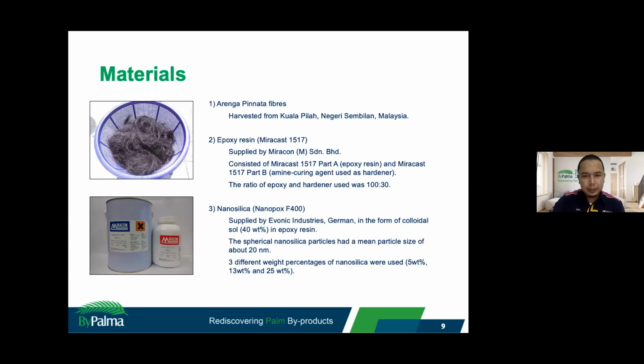So these are the materials. First, Arenga fibers. Second is epoxy resin, and third is nanosilica. Arenga Pinnata fibers were harvested from Kuala Pilah, Negeri Sembilan, Malaysia. For epoxy resin, we use Miracast 1517, which consists of part A, the epoxy resin, and part B, the hardener. The ratio of the epoxy and hardener used was 100 to 30. Next is nanosilica, Nanopox F400, in the form of spherical shape with the mean size of 20 nanometer, and we dilute the nanopox into 3 different weight percentages of nanosilica, which are 5 weight percent, 13 weight percent, and 25 weight percent.